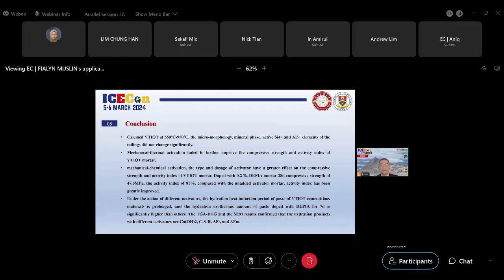Doped with 0.2% DEIPA mortar, the 28 days compressive strength is 47.6 MPa and the activity index is 85%. Compared with the mortar without activator, the activity index greatly improved. Under the action of different activators, the hydration heat induction period of paste with VTIOT cementitious material is prolonged, and the hydration amount of paste doped with DEIPA for 7 days is significantly higher than others.